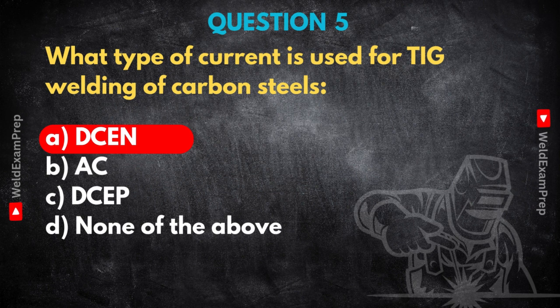You'd likely see the tungsten tip looking melted, maybe balled up instead of nice and sharp like it should be for DCEN. It's probably the most common electrical mistake for beginners on TIG with steel, just forgetting to set the machine to DCEN, or maybe leaving it on AC after doing an aluminum job. Understanding that link between current type, heat focus, and penetration is vital diagnostic knowledge.